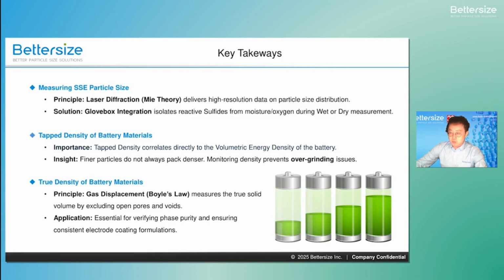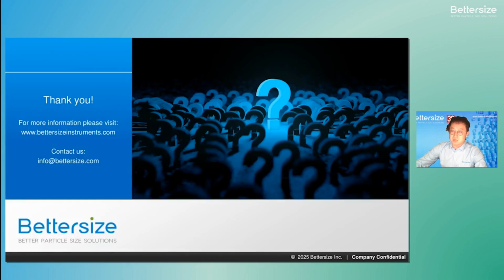Finally, for true density, we utilize the gas displacement method based on Boyle's law. This allows us to look past the air gaps and measure the solid material itself, giving you an absolute baseline needed for phase purity and coating consistency.